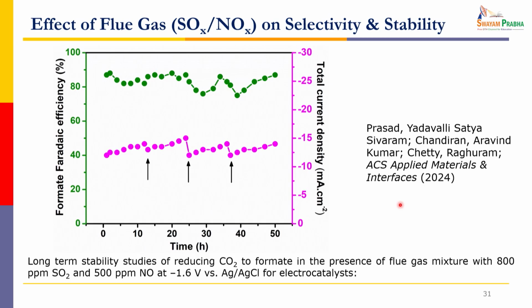We have done this experiment for 50 hours where you pass carbon dioxide in one of them, or carbon dioxide plus SOx plus NOx, and you can see the Faraday efficiency. There is some minor variation that is expected, but overall the Faraday efficiency is close to 80%. So there is no change in the Faraday efficiency for over 50 hours. This is for the bismuth catalyst. We did the same for the tin catalyst, but the tin catalyst was stable only up to 20 hours, whereas the bismuth catalyst stayed stable close to 50 hours with no decrease in performance. And so this is one of the good ones.